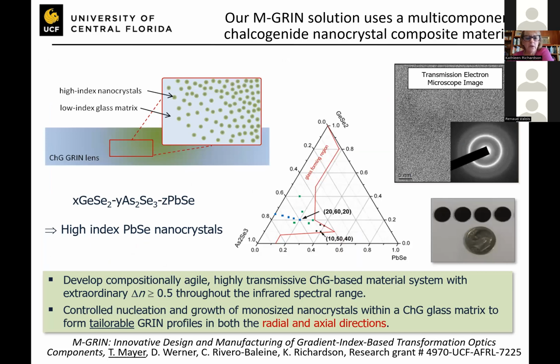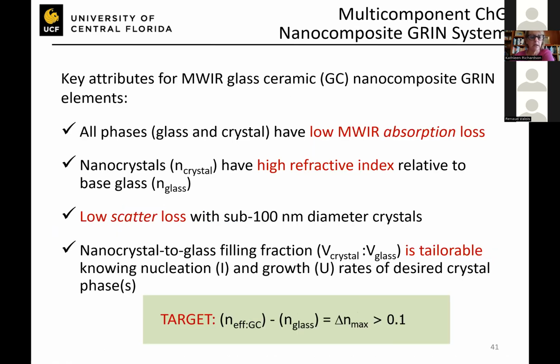And then lastly, we have done a lot of work on laser writing of metastructures, and I'll finish by talking about this. Here's an illustration of some of these gradient index glass ceramics, and we call these composites, where because we understand how we can use a laser source to nucleate and subsequently grow nanocrystalline materials in a homogeneous glass material. We start with a glass, we nucleate and grow these crystallites shown as green circles. We can change essentially the volume fraction and therefore the effective refractive index in this glass ceramic. So suffice to say, the more high index crystals you have in a low index glass, the higher the effective refractive index will be. So now I have a way, as long as my laser light can penetrate through my thick glass sample, to make a gradient by spatially controlling this in both axial and radial directions.